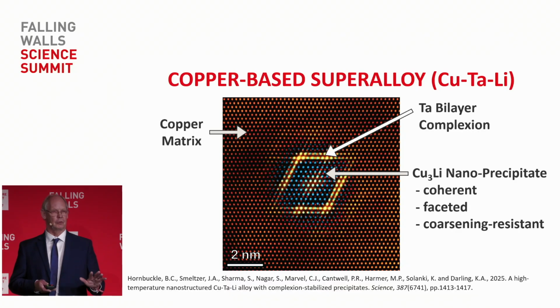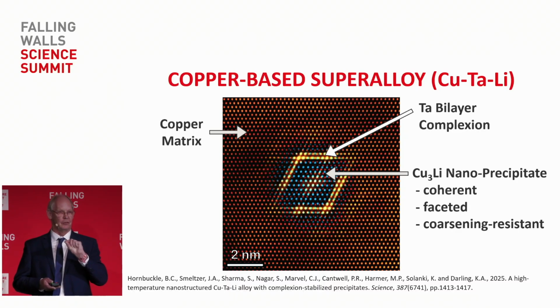So we see an atomic resolution image now of what happens when you further add the lithium. In the image, in the middle of that particle, that precipitate phase, you can see its bluish regions. It is reacting with the copper to form Cu3Li, which is gamma prime, which is why I mentioned it earlier. So gamma prime forms as the phase, and the energy between the gamma prime phase and the copper matrix is high, and to lower that energy, it forms a complexion at the interface, which is a bilayer of the tantalum.